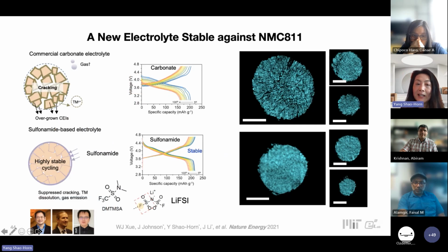We can utilize such a solvent and test it against NMC 811. And you can see that such a solvent, with a similar molecular structure, with the salt lithium FSI, right? Both molecular structures are essentially free of oxygen, and maybe free of hydrogen that may be subject to oxidative dehydrogenation. And we see much improved stability relative to a carbonate solvent.